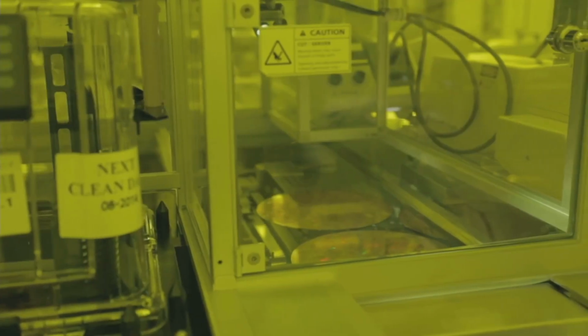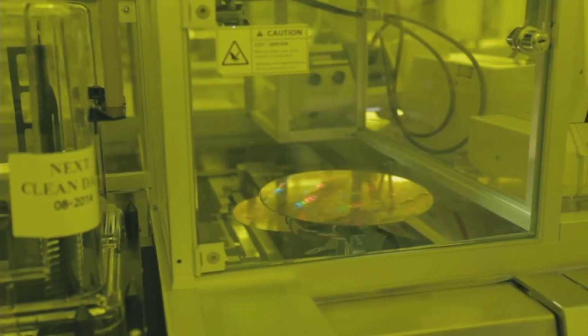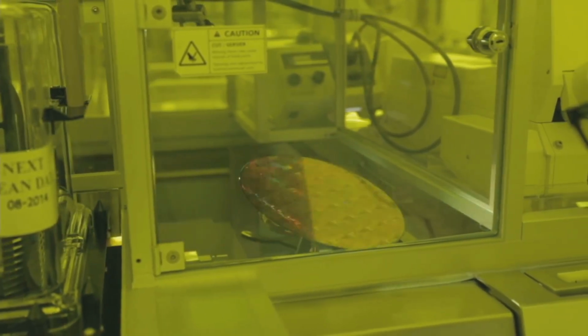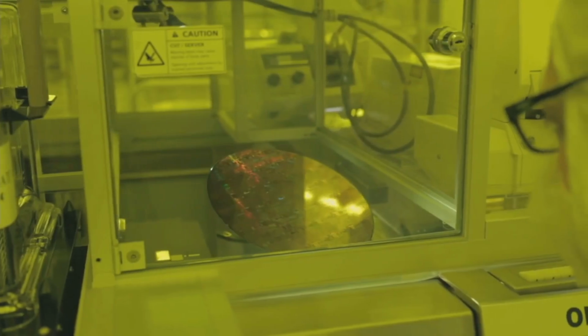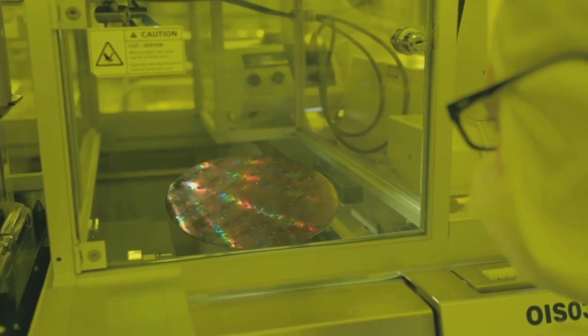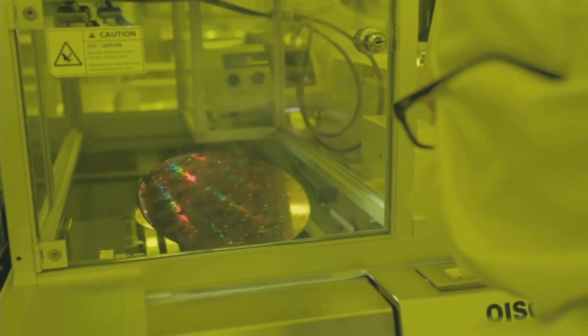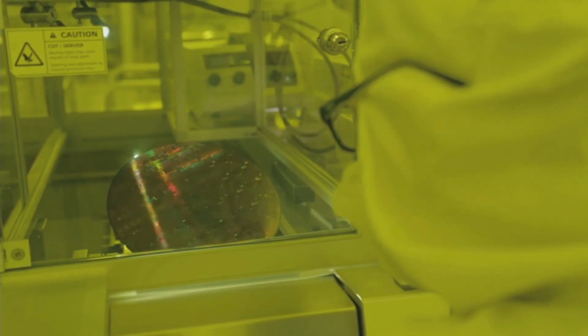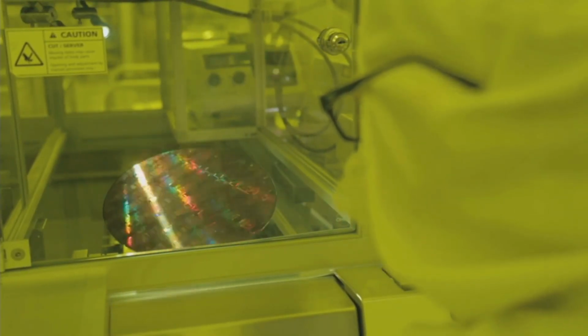Since the mid-1990s, laser diode manufacturers have bonded synthetic diamond heat spreaders directly to the back of their chips. Diamond conducts heat at roughly 2,000 watts per meter per Kelvin, 5 times better than copper. The heat leaves the die immediately, spreads laterally across the diamond, and enters the downstream cooling structure at a lower temperature and a wider area.